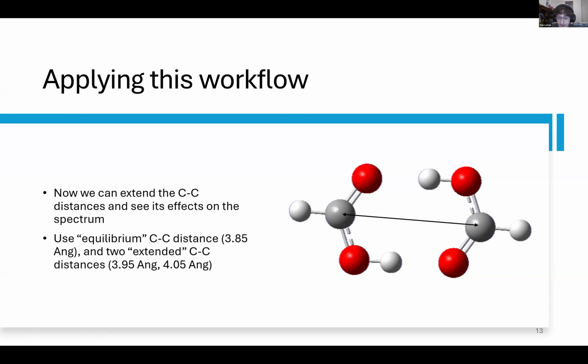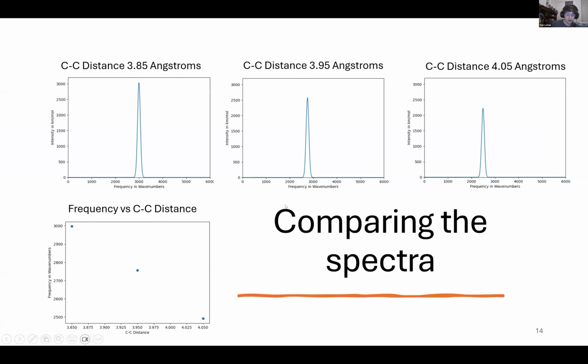Now I'm going to extend that to 3.95 angstroms, 4.05 angstroms, and see how the frequency of the peak is affected. So what do we actually see? Well, the frequency is definitely decreasing with increasing CC distance, and it is an extremely nice relation. You can see the specific spectrum on top. You can see the relation on bottom. Looks very nice.